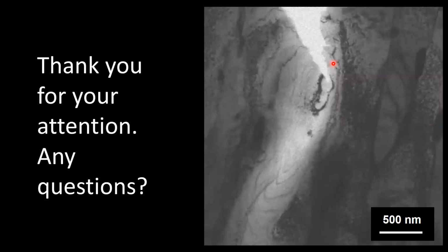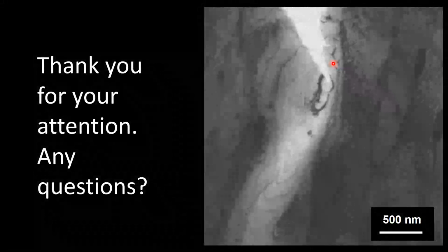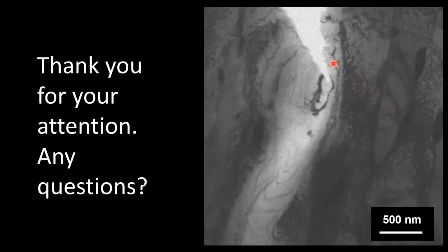We can see the increase of lattice constant with the increase of hydrogen exposure pressure. So maybe there is something to do, like bulk, and then compare with what you see in situ with the TEM. But the point about the shear modulus is that I've been reading a book made mostly by chemists about hydrogen embrittlement, and it seemed obvious to them that the bond would change from a more metallic aspect. It will switch between metallic and covalent bond, from one to the other.